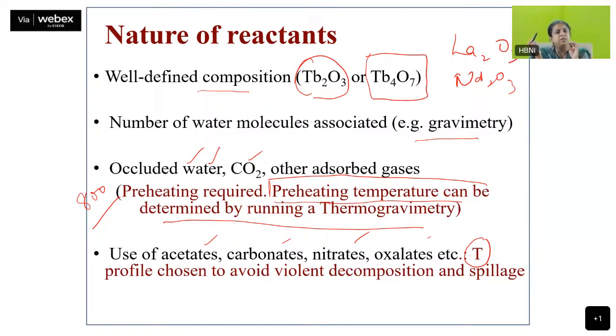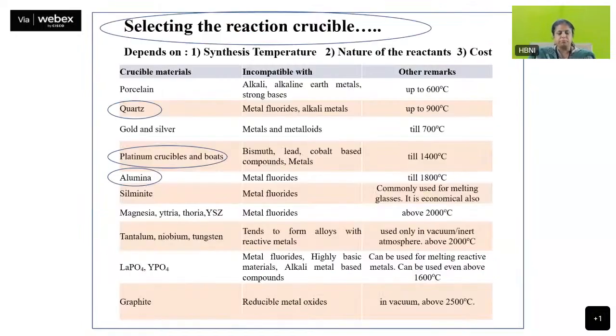Good solid state chemists do not set a very high temperature rate because it affects the furnace. But other than that, if you have chosen a very high heating rate due to some requirement, then at the decomposition temperature, the rate of increase of temperature being very high will cause violent decomposition and the material will spill out, because barium carbonate or acetate will evolve CO2, CO and all that. So the temperature profile has to be chosen very carefully.